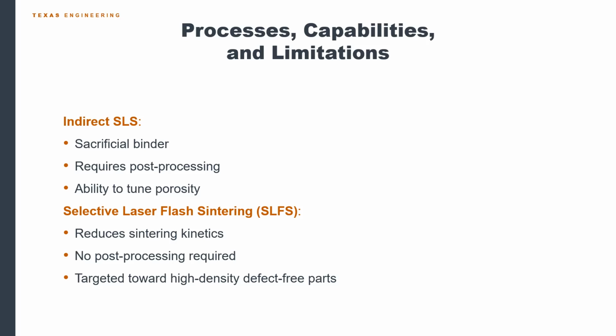So you kind of need to engineer some ways around that. And we have two ways that we work on primarily. The first one is indirect selective laser sintering, where we add a sacrificial binder so that when we scan it with the laser, only the sacrificial binder melts and forms bridges between the ceramic particles. But this method does require some post-processing, but we do have the ability to tune the porosity, and I'll talk a little bit about that next.